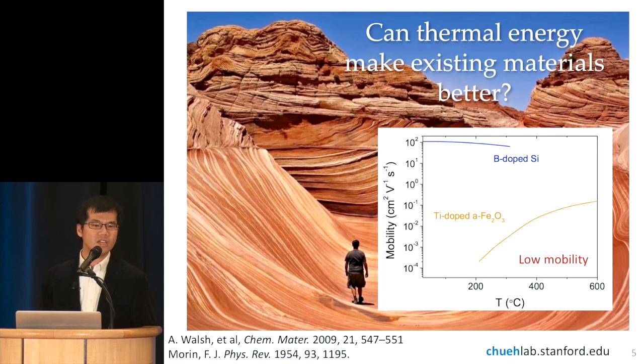And one of the initial ideas we had was to look at how transport properties of semiconductor depend on temperature. So as it turns out, many of these oxides, which are earth abundant, also have very low charge carrier mobility, which means it's hard to take the electrons or holes out of the material without them recombining and thereby converting them into heat. And this is just a plot of the mobility comparing silicon and iron oxide.